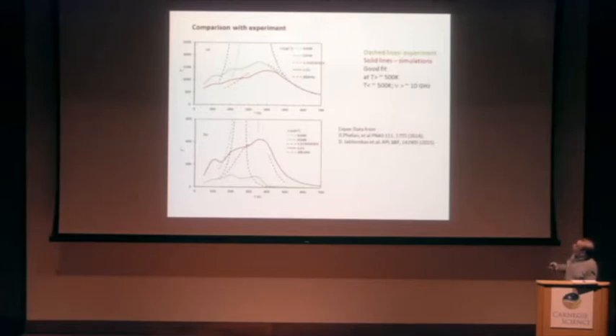Here you can see dashed lines are experiments from these papers, and solid lines simulations. The same color corresponds to the same frequency, and you can see that at high frequency, the correspondence between experiment and calculations is very good, especially above 500. At low frequency, the correspondence is not so good. It's clear because we cannot simulate very low frequency. We need very long time for simulations.